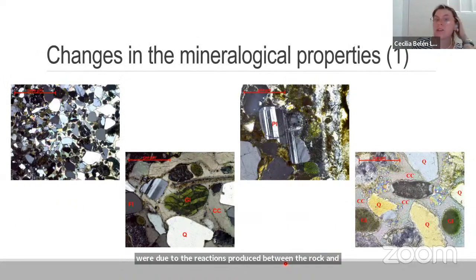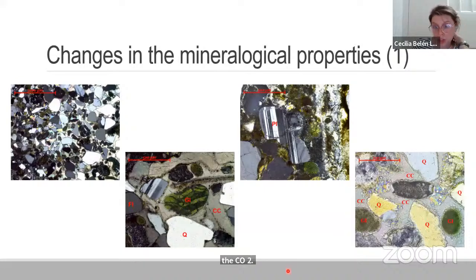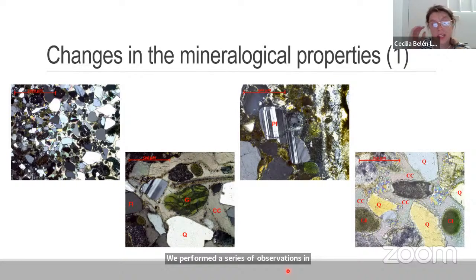We performed a series of observations in the microscope, analyzing thin layers of the sandstone studied. In this particular presentation, I will only be sharing the results obtained in pristine samples. We were able to observe that the samples presented quartz, which is reasonable as we were working with sandstone.